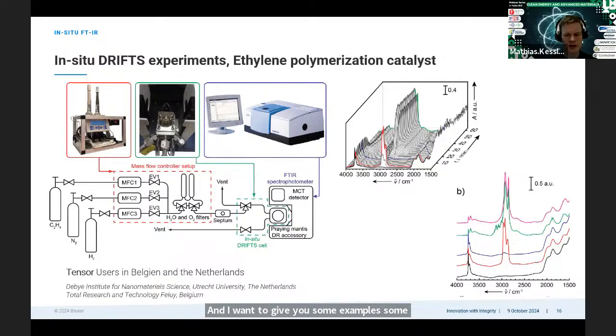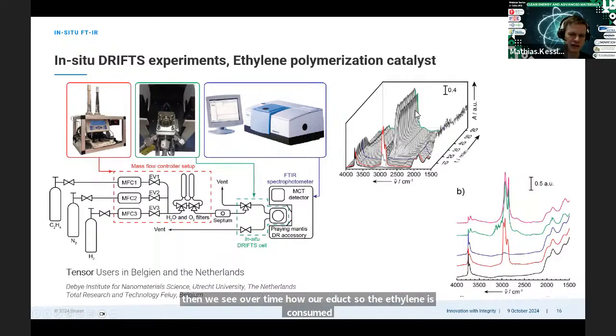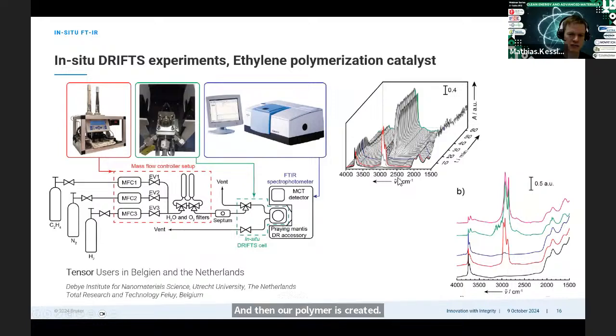We can do our in situ measurements in different ways. So this is the first possibility here. We use a Tensor system and we use repeated measurements simply. And the observation of the experiment is done for an ethylene polymerization catalyst. And then we see over time how our educt, so the ethylene, is consumed, and then our polymer is created. And we can track this reaction over time. The scale of the time axis is in minutes. So we track here the reactions slowly with repeated measurement.